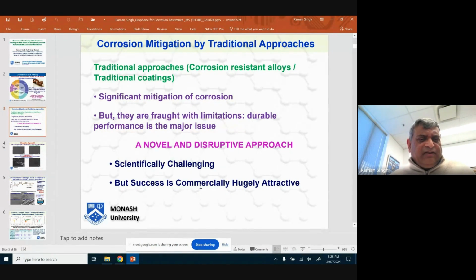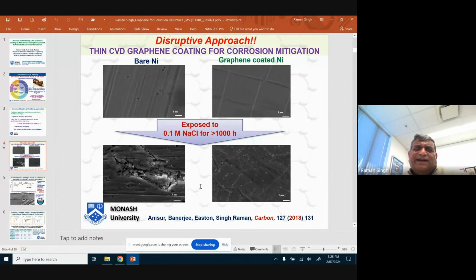So with that background, what I'm going to show you today is that if you have a bare nickel and it is exposed to something like seawater for, say, a few hundred hours, you will have huge corrosion attacks on the surface of bare nickel. But if you had graphene coating on nickel, it does not corrode at all. It resists corrosion in a big way.